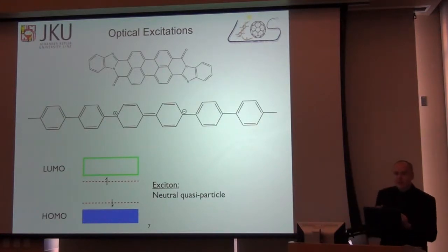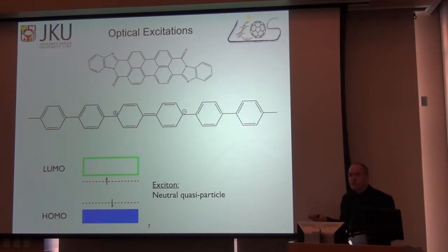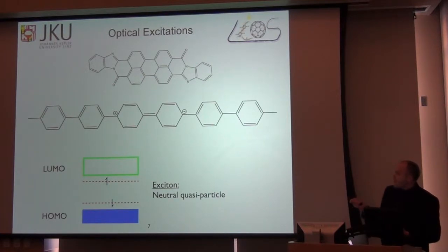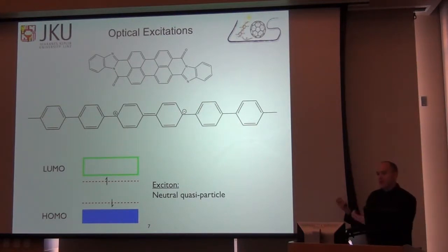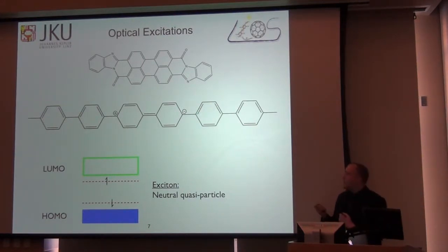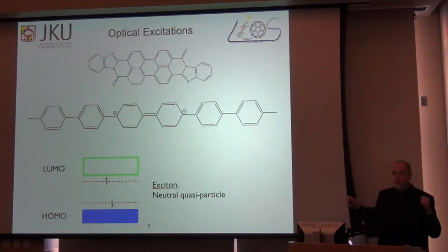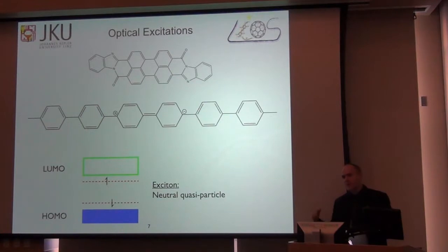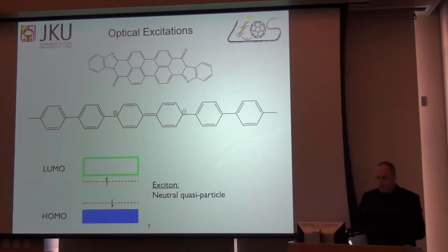So this forms not a free carrier, but what is called an exciton, a tightly bound Coulombic quasi-particle, and that is neutral. And so if you apply an electric field, it doesn't move because the positive and negative charges move in parallel. And so on a polymer, you get the same thing. You wind up with this dislocation, a change in the orientation of the pi electrons. But even if the positive and the negative charges were separated as far as they could be, separating them further would cause a drastic increase in the lattice energy, which doesn't happen. So these things feel a lattice and a Coulombic confinement, which render them tightly bound excitons.